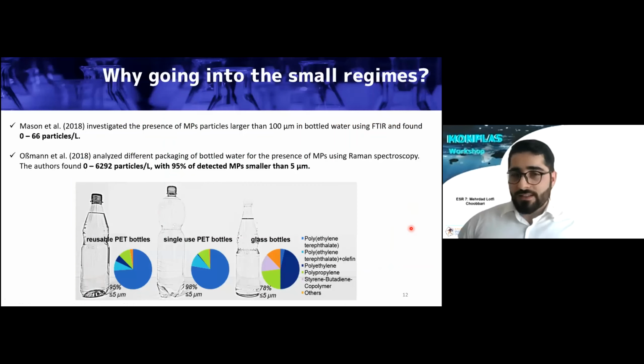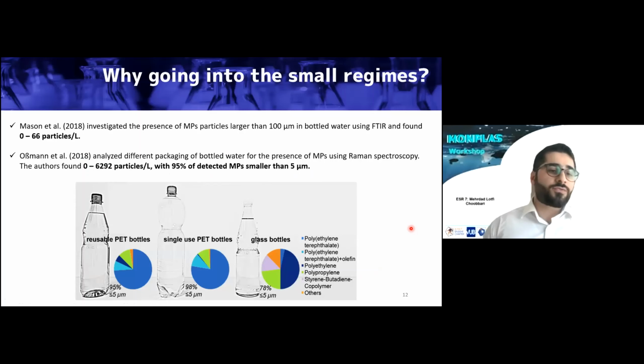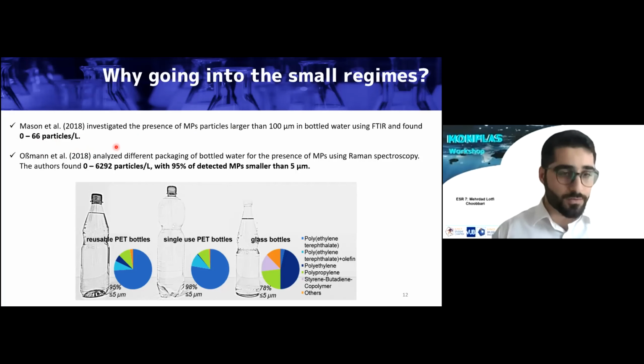To better understand it, let's look at some findings from some works which have been done already in this field of research. In one study in 2018, the authors investigated the presence of microplastic particles in bottled water, and they targeted the particles larger than 100 micron. And they used Fourier transform infrared spectroscopy to analyze these particles, and they found a range of 0 to 66 particles per liter in this bottled water.